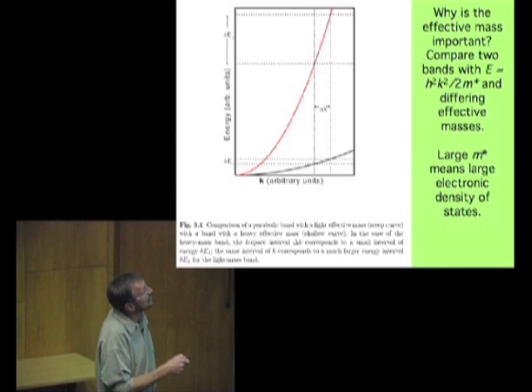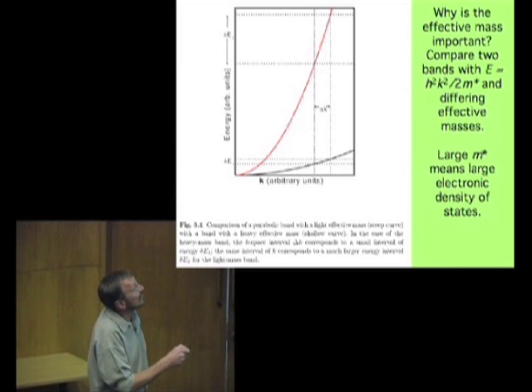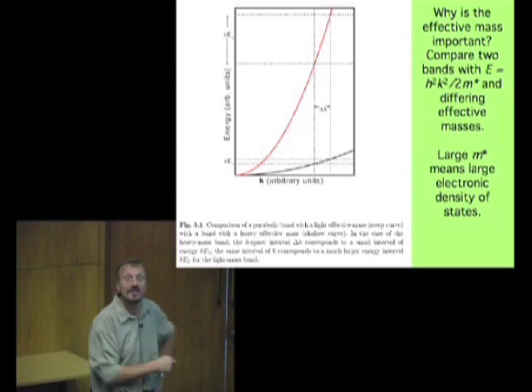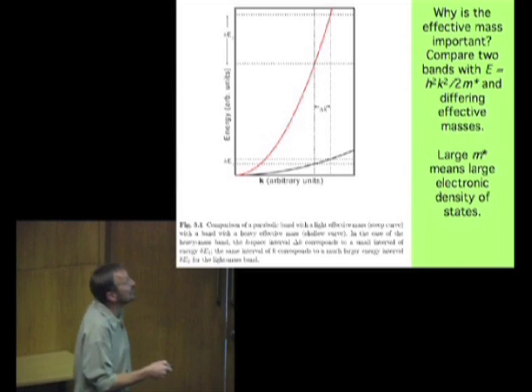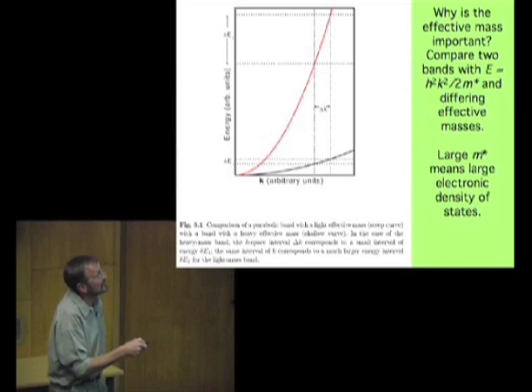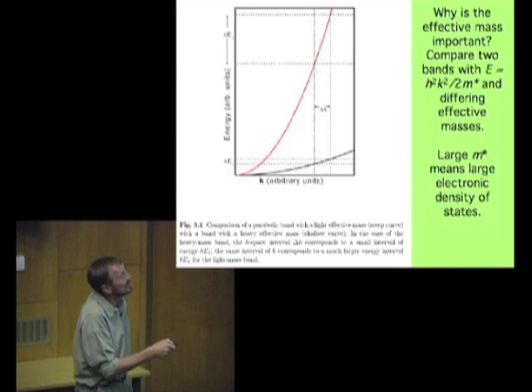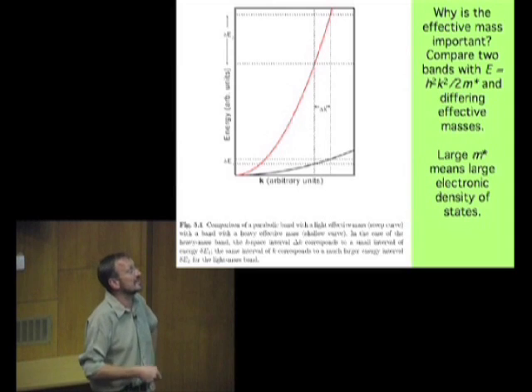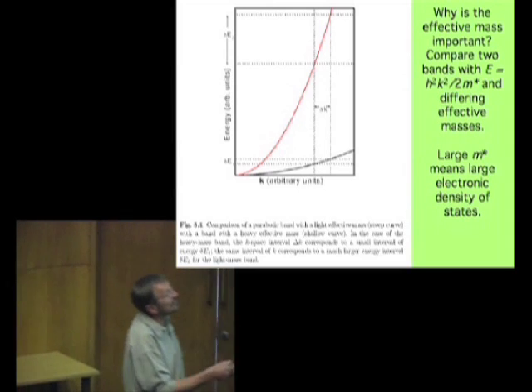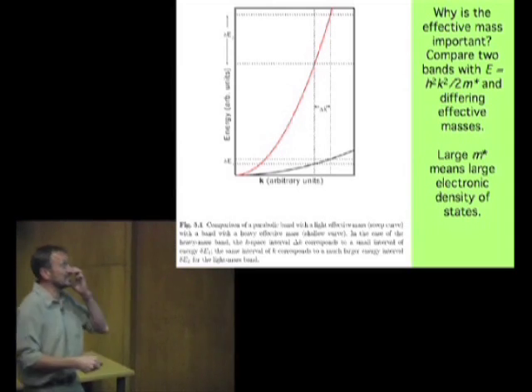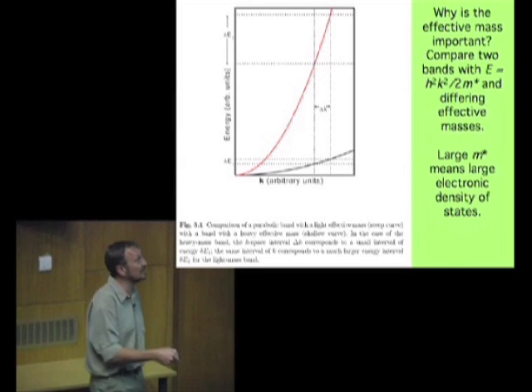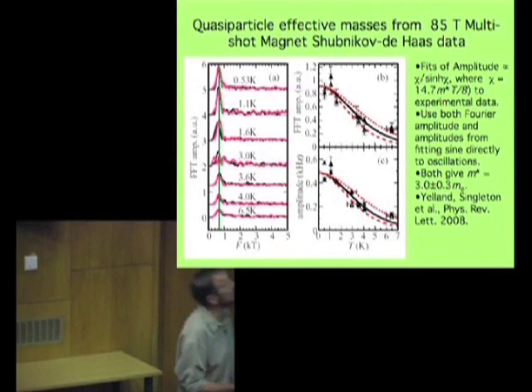So if you look at this region of K-space here, and we look at the light effective mass band, you can see that this width of K-space occupies a big range of energy. That means the density of states is low. If we look at the band with the heavy effective mass, this same width of K-space, wave vector space, occupies a narrow range of energy. It has a large density of states. So a large effective mass means a large electronic density of states, which means it's important to know if you want to do a model for superconductivity.